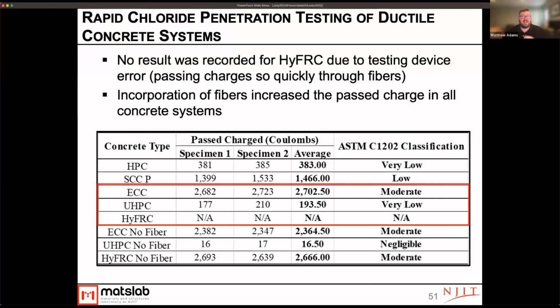So what we do see is that our systems with fibers, particularly the ECC, had a fairly high charge passed, and even with the UHPC, we do see about 10 times the charge passed than when we didn't have fibers. The high FRC system, which has metal fibers in it as well, we actually couldn't get a read on because it was passing so much charge through that network of metal fibers. And so with the high FRC, you absolutely cannot use this test method for measuring the chloride performance with the fibers in it.